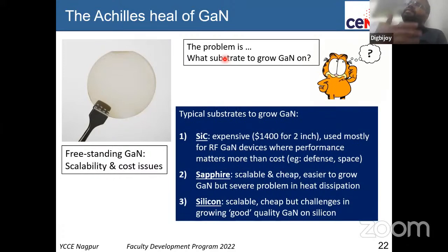So typically people grow on silicon carbide. It's very expensive also, but it's a very good substrate. People in the defense industry, where cost does not matter, use silicon carbide to grow gallium nitride. Very good devices are formed. Sapphire is very cheap like silicon, but the problem is sapphire cannot withstand heat. And these transistors are for high voltage, high power, so heat is there. So sapphire is not good because it cannot handle the heat.